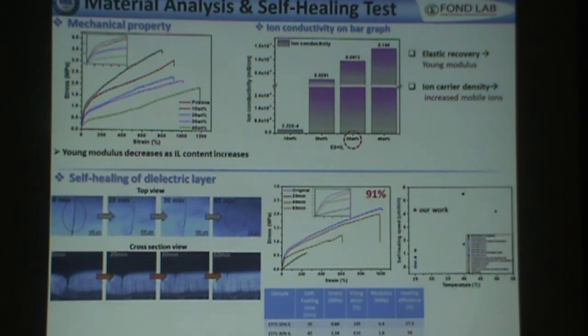Because we introduced the chlorine functional group, and in the TPU structure we had a hard segment as well as a soft segment, these components ensure that we have a good elastic deformation property. So there isn't much of wrinkles or cracks, unless we crack it by ourselves, which means that we are doing the self-healing test. Besides that, any micro cracks are really negligible because of the hard segment and soft segment components in the TPU matrix.